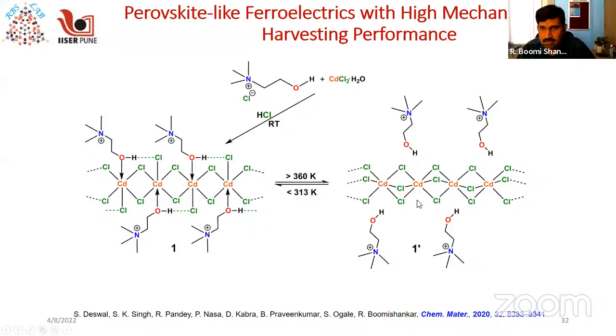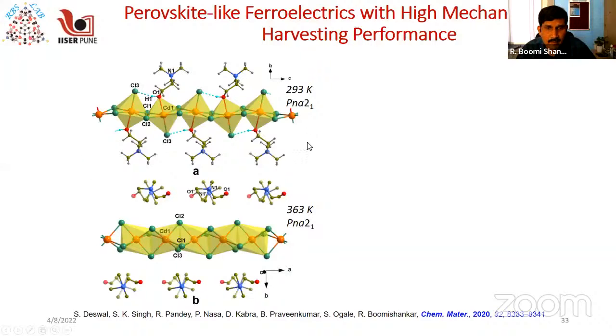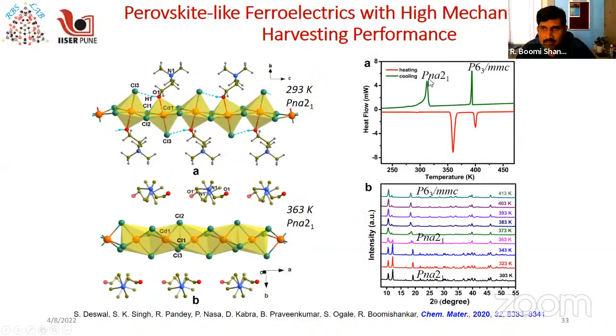In the normal perovskite, the cadmium centers are connected by 3 chloride bridges in a face-sharing fashion, whereas in this case, the cadmium centers are connected by 2 chloride ions in an edge-sharing fashion. The third chloride ion is terminal, and it is hydrogen bonded to the hydroxyl group of the ammonium cation. So this molecule goes from the modified perovskite to a normal perovskite at higher temperatures, because the coordination is lost at higher temperatures. We have mapped this crystallographically, and we can also see the different phases present in the material using